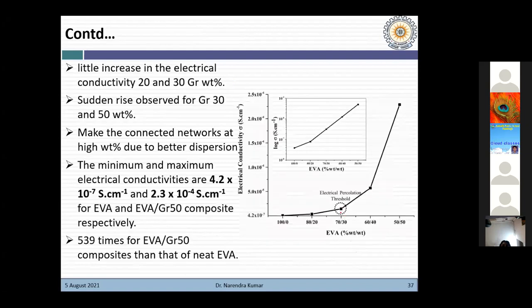So in our case, we got the electrical percolation threshold value at this point, 70-30, right? And we also compared the electrical conductivity of neat EVA with that of graphite filled EVA. We observed a 539 times improvement in the electrical conductivity as compared to neat EVA.